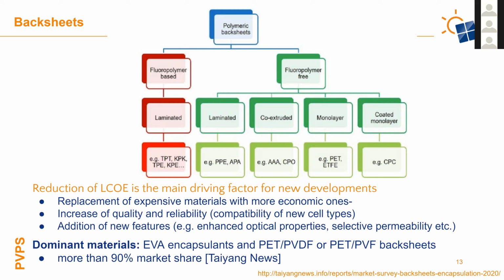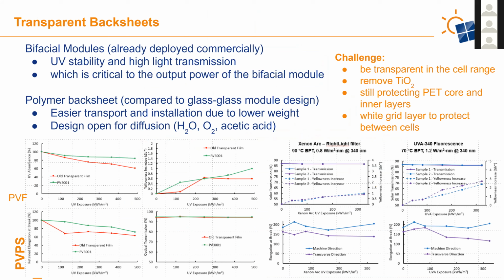One new technique out there is transparent backsheets, important for bifacial modules which are already being deployed commercially and used. Instead of a glass back, you can use this polymer back, which is easier for transportation because they're thinner and lighter, so you can install a little easier. They also allow diffusion of water, oxygen, and acetic acid much easier out of the material compared to glass.